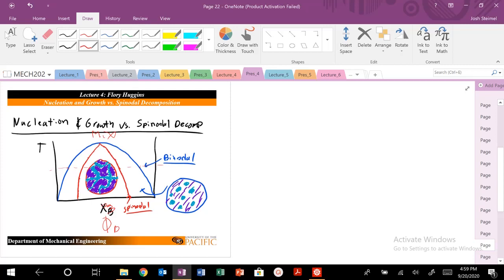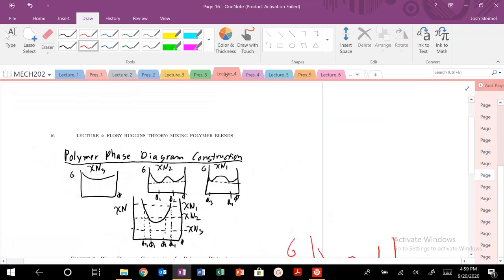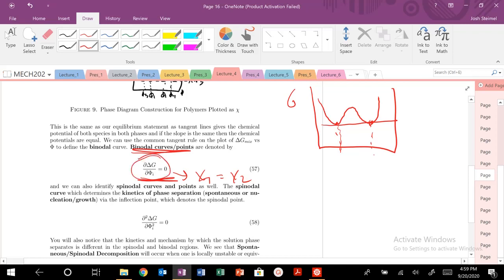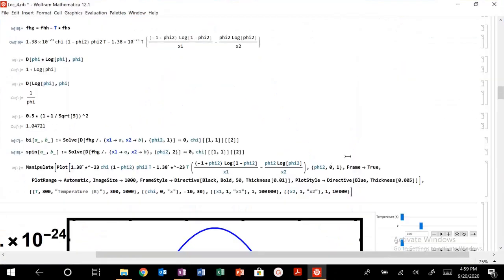We'll talk about what it means in terms of how the material will phase separate — will it phase separate stably or unstably? Will it spinodally decompose, or will it perform nucleation and growth? The condition: we can find the common tangent, and the common tangent slope will equal zero when x₁ equals x₂. When my degrees of polymerization are the same, I can use this equation.